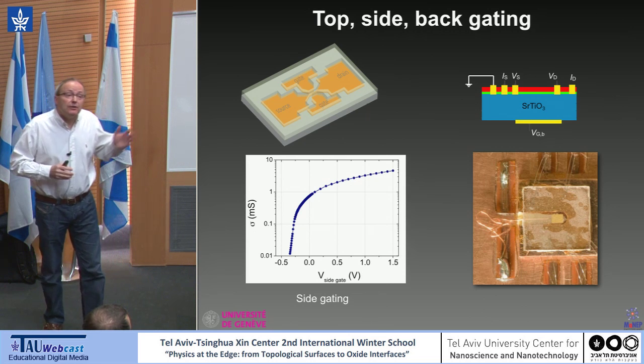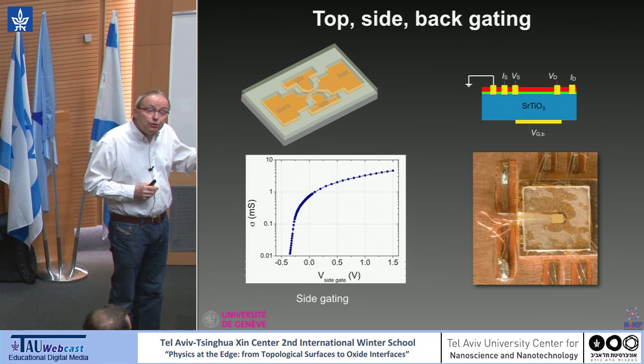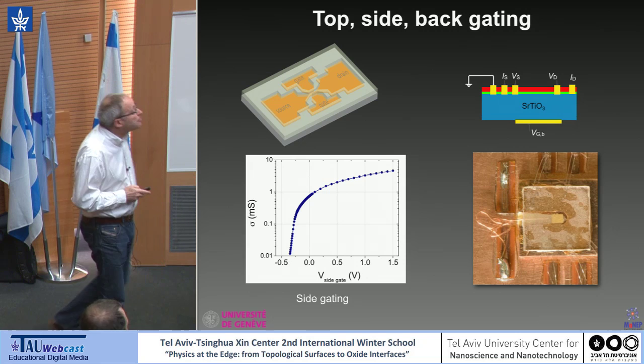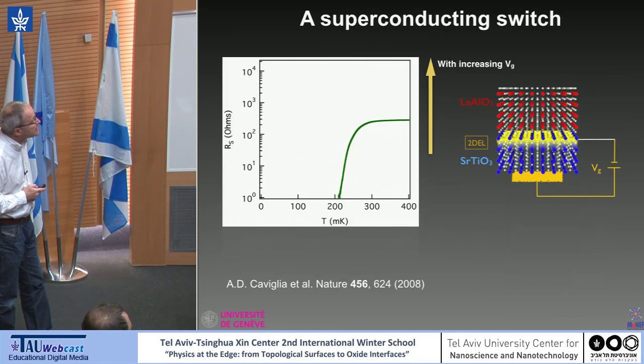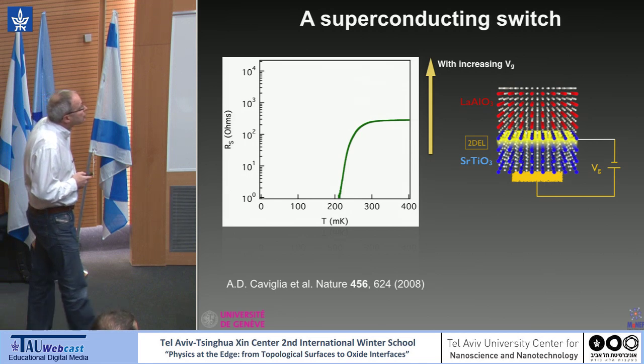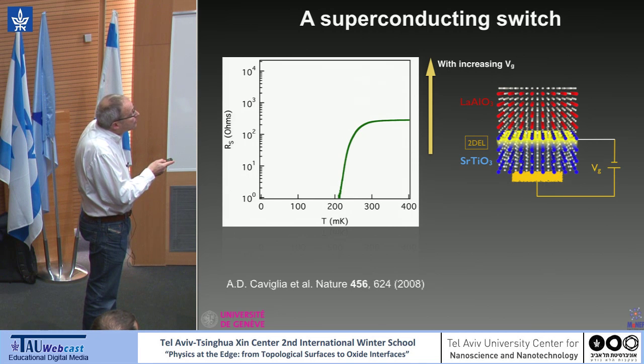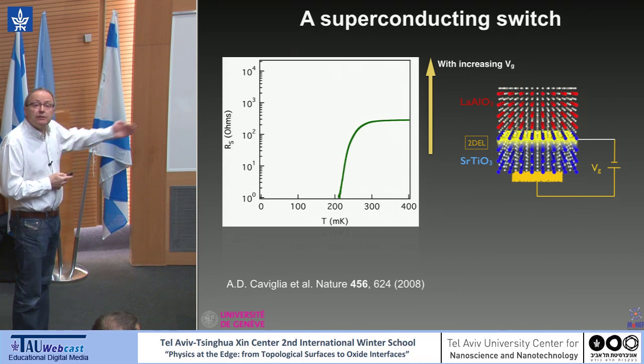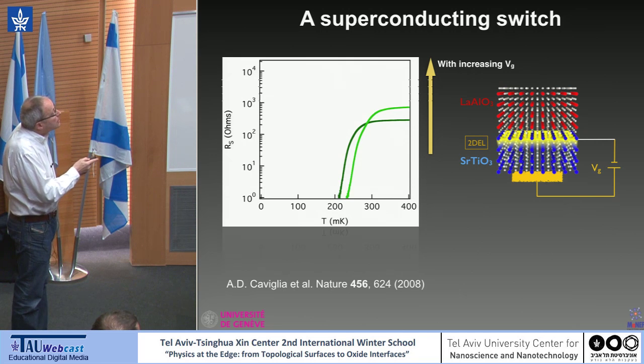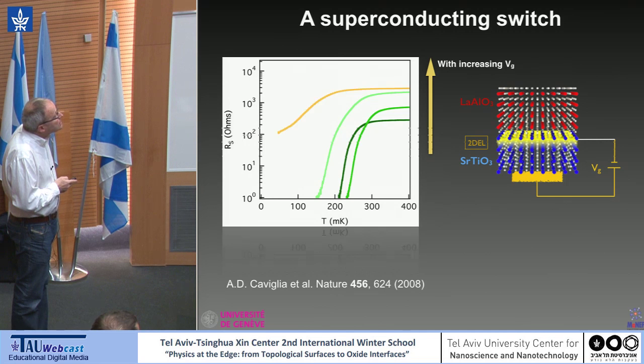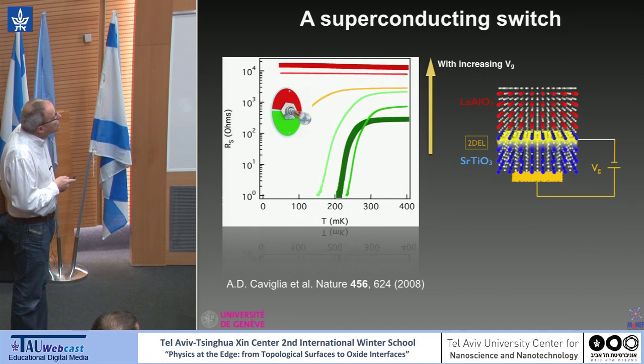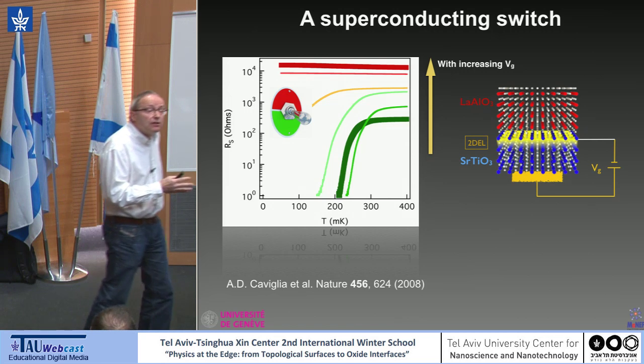Now, you can perform this field effect experiment, you can tune the carrier density. What will happen to superconductivity? I'm showing this on this slide. This is a curve measured with 0 volt applied. We have a back gate in this configuration, so on the back side of strontium titanate. Then I'm reducing the carrier density, and you see that the resistance is going up, which makes sense. Here TC is going up a little bit, but then TC is going down, and you lose superconductivity. What we have here is a superconducting switch, which allows the on-off switching of superconductivity.